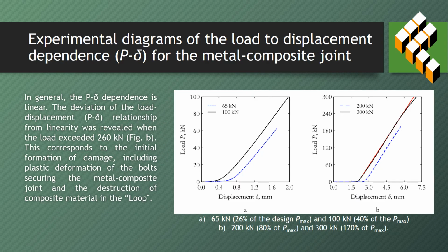In general, the load displacement dependence is linear. The deviation of the load displacement relationship from linearity was revealed when the load exceeded 260 kilonewtons. This corresponds to the initial formation of damage, including plastic deformation of the bolts securing the metal composite joint and the destruction of composite material in the loop.